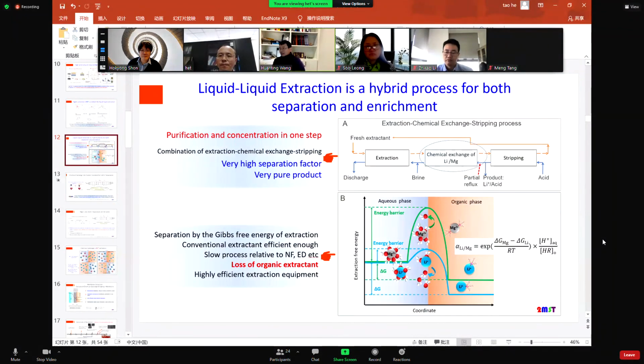Yeah. So how do you get a solid out? Because for the lithium-ion battery, you need either lithium carbonate or lithium hydroxide. So how do you get lithium out of the liquid? If you look at this graph, it can give you some hints. You see here extraction, chemical exchange for lithium and magnesium. So we get a pure lithium to the stripping phase. In the stripping phase, we have acid, basically hydrochloric acid. So the hydrochloric acid will exchange with the lithium inside the organic extractant. So we get a hydrochloric acid lithium chloride solution.